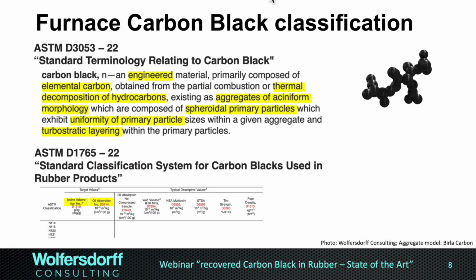And there's really two target values that classify the furnace carbon blacks. On the one hand side the iodine adsorption. That is an old test method which is no longer used that much because it can be tricked by the surface groups on the carbon black. Nowadays, people use the BET, Brunauer-Emmett-Teller nitrogen adsorption to tell about the specific surface area. And we got the oil absorption, which is a measure for the structure of the carbon black. And then, depending on those two, we have all the carbon blacks defined.